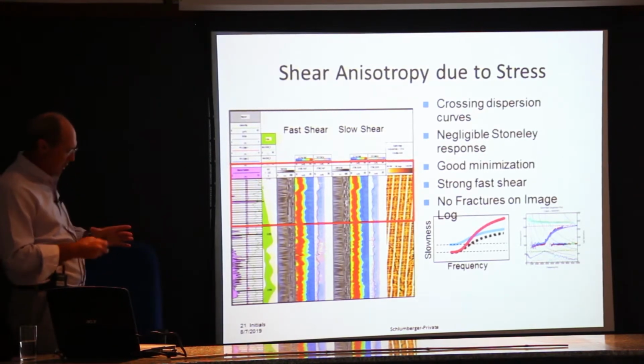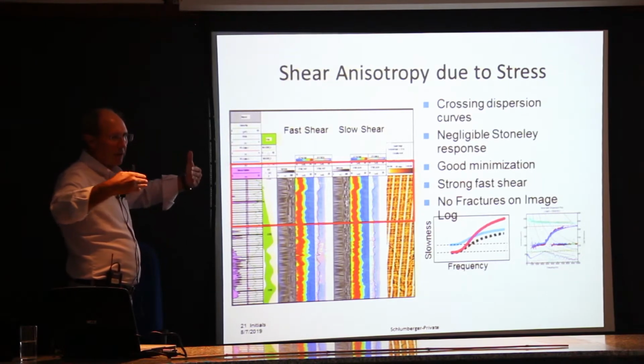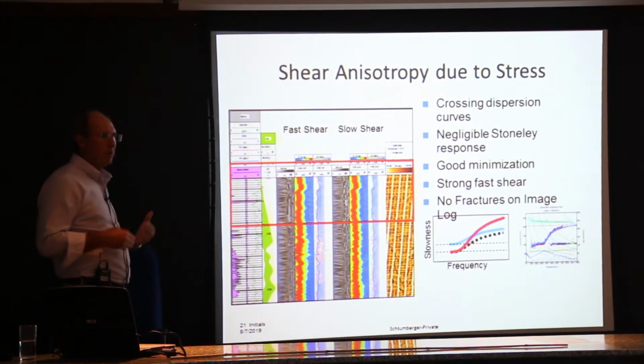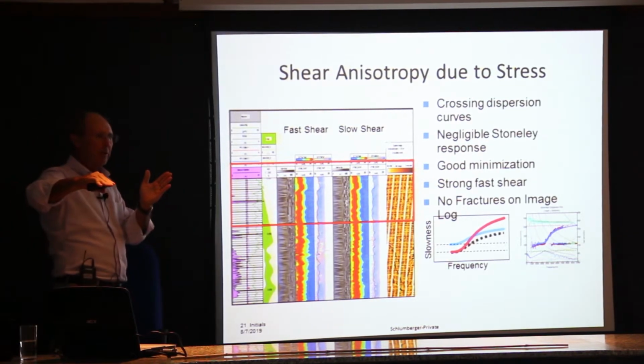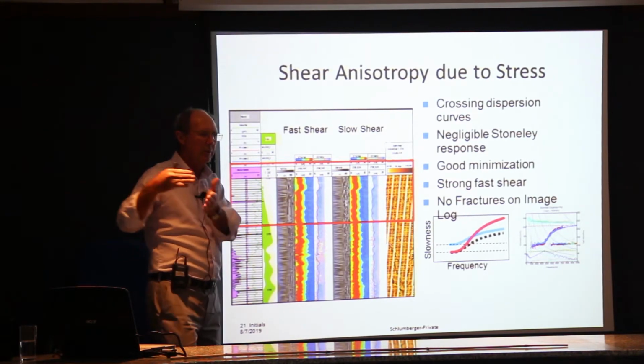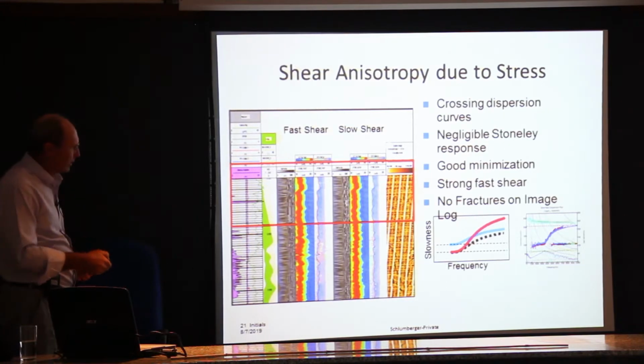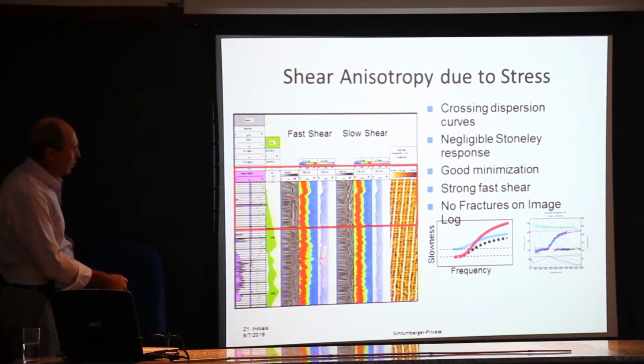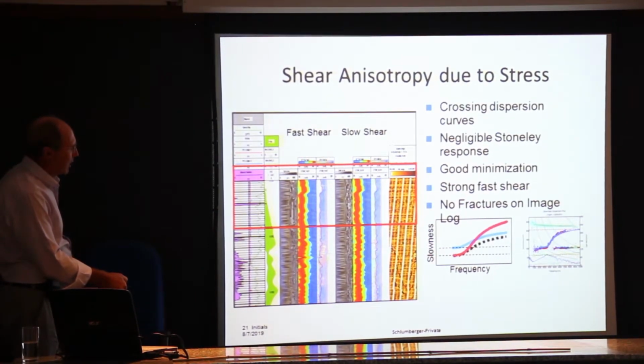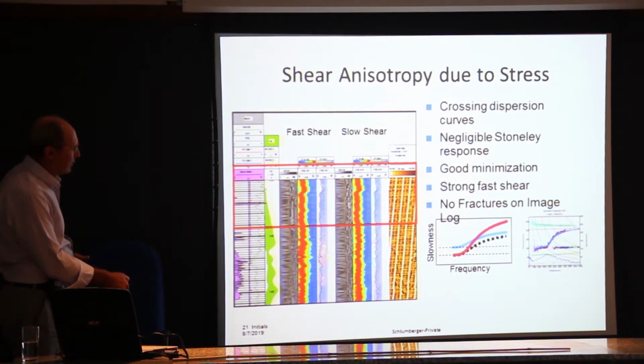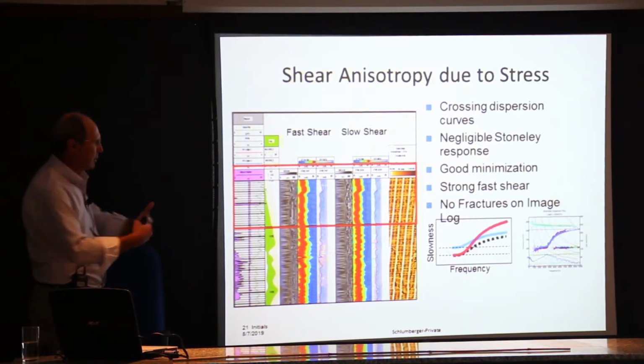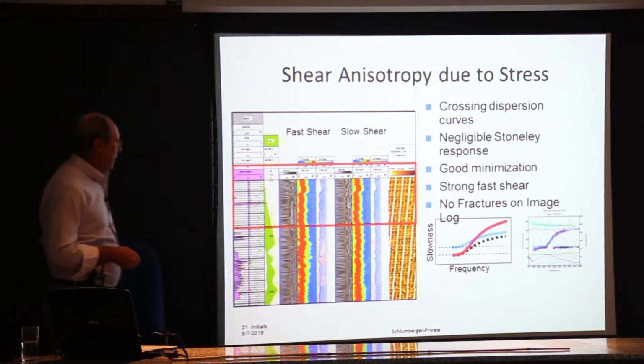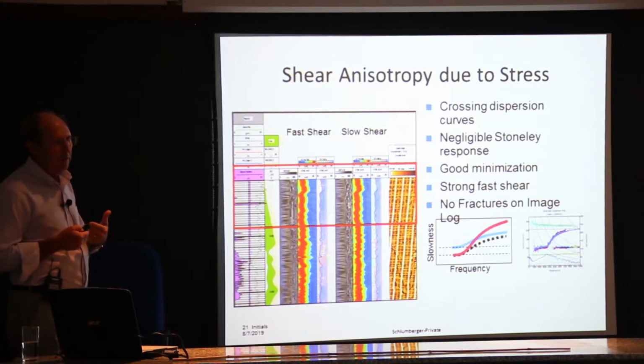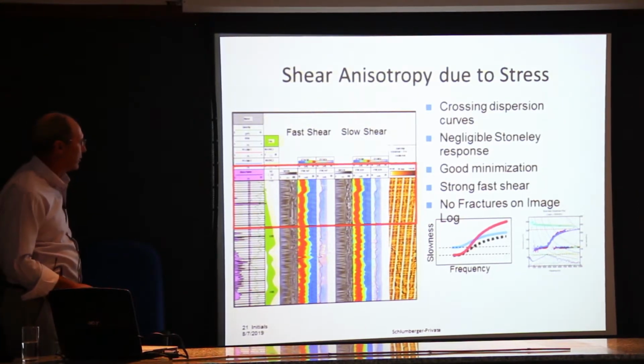And this is because of the hoop stress effect. If you've got uneven downhole stress, it gets magnified due to the hoop stresses at the wellbore, and then it decays as you go away into the far field. So near wellbore, the stress direction is 90 degrees different from the far field, and that 90 degrees difference leads to this crossover effect. So near the wellbore, you get the fast shear here, but as you move further, the far field, the low frequency, you see the true fast and slow shear. But as you start to feel the hoop stresses and get near the wellbore, you get this reversal in the fast and slow. So we use this in the pre-salt to better understand what are natural versus what are drilling-induced fractures.